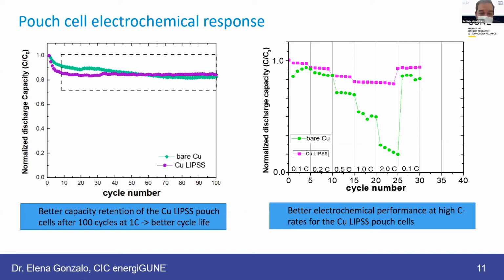as the cycling test was very fast, there is a small fluctuation of the data due to the temperature conditions of the room. So at the very beginning, the bare copper foil was performing better. It was giving more capacity, more electrochemical response, but at the end of the test, the stability was improved when we were using the copper LIPSS. These small undulations could be due to the temperature, but in both cases, they were tested at the same conditions.